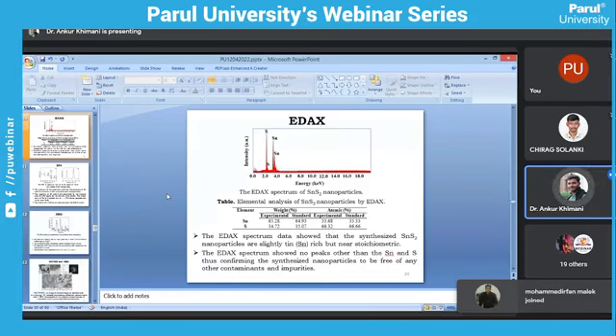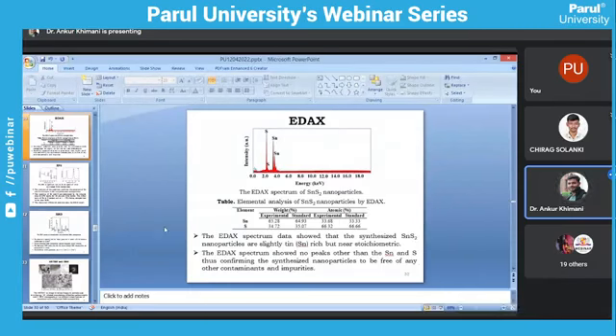Then this grown nanoparticle is characterized by EDX for chemical identification. The EDX spectrum of SnS2 nanoparticle is shown over here, the intensity versus energy graph. Over here, the elemental analysis of SnS2 nanoparticle by EDX, with weight percentage and atomic percentage. The EDX data shows that the synthesized SnS2 nanoparticles are slightly tin rich but near stoichiometric. The EDX spectrum shows no peak other than Sn and S, thus confirming the synthesized nanoparticle to be free of any other contaminant or impurity.